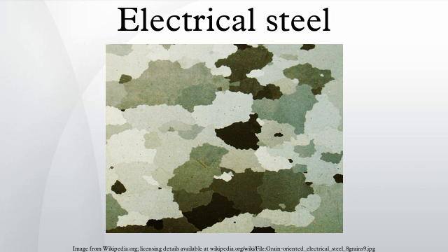Silicon significantly increases the electrical resistivity of the steel, which decreases the induced eddy currents and narrows the hysteresis loop of the material, thus lowering the core loss. However, the grain structure hardens and embrittles the metal, which adversely affects the workability of the material, especially when rolling it. When alloying, the concentration levels of carbon, sulfur, oxygen and nitrogen must be kept low, as these elements indicate the presence of carbides, sulfides, oxides and nitrides.